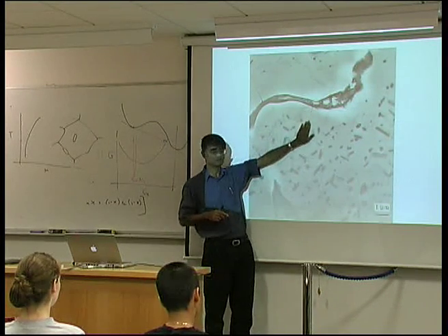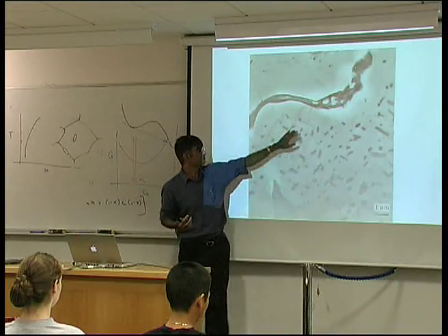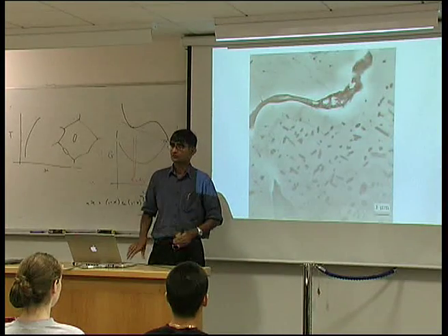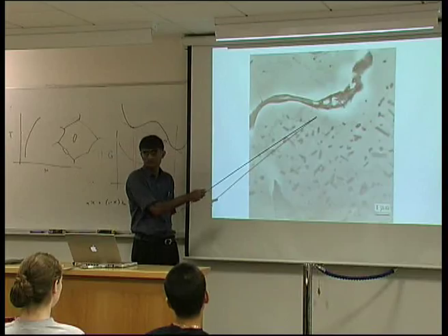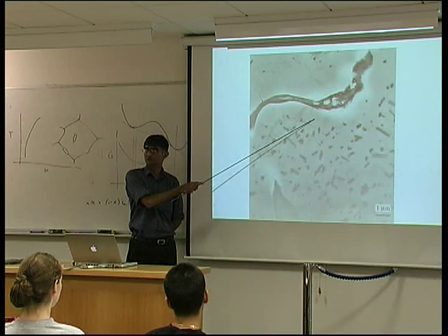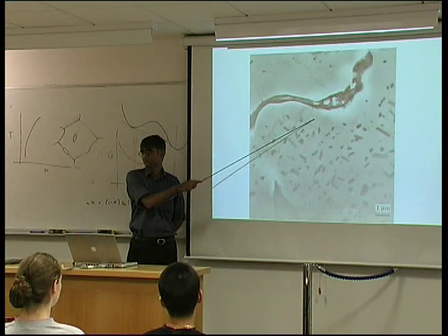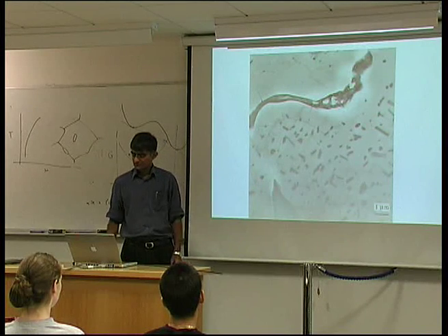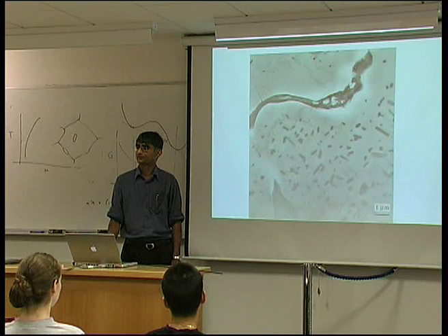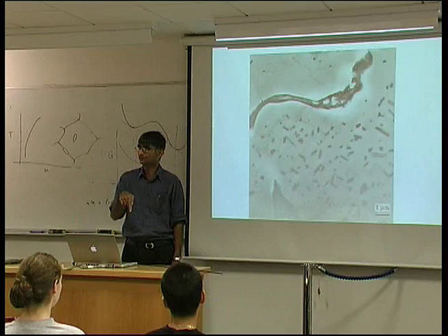And as it forms, it draws solute from here and here. And therefore, you remove supersaturation from that region, and you don't get any precipitation. So you've got strong matrix, soft area near the grain boundary. It's the worst possible scenario, because you will focus strain when you deform it in that region. Is there any other mechanism by which we get precipitate-free zones? One is solute depletion because of precipitation at the boundary.